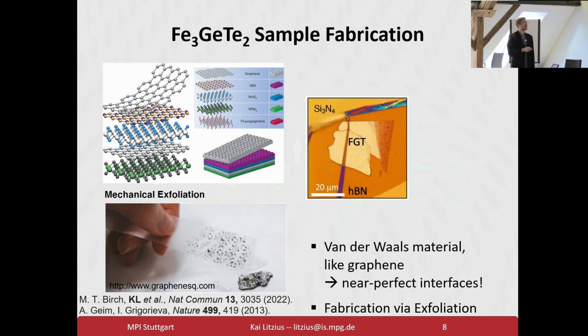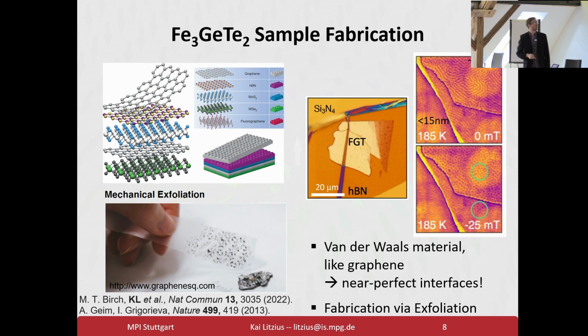So this is what a flake usually looks like in our experiment. Optical image, where we see here, this is the magnetic material laying on the membrane. And if you look at it magnetically in the chamber, then you see here, for example, stripe states or skyrmion states, depending on the conditions. Sorry, the brightness is not really good for the image right now. So we exfoliate them, we generate flakes, we generate devices out of them, and then we look at the magnetic texture inside. So now let's talk about what this texture, what the state diagrams look like and why we need to know the history dependence of them.